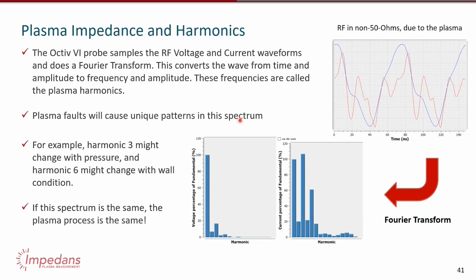With a VI probe, instead of using peak detection methods, I recommend you use Fourier transform methods. If you apply a Fourier transform to a waveform, you go from time space to frequency space, so you get a spectrum. What I have here on the left is a voltage spectrum, and on the right is a current spectrum. The first bar represents 13.56 megahertz, and the second bar is 27.12, 40.68, and so on. Again, the fundamental frequency comes from the generator, and the harmonics come from the plasma.